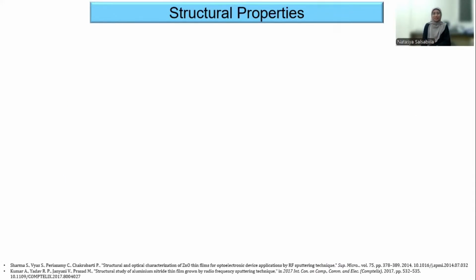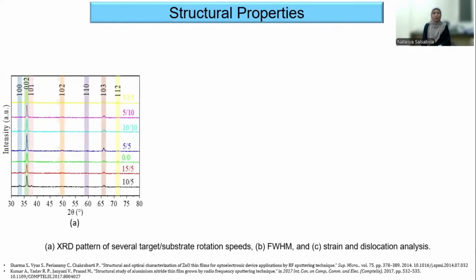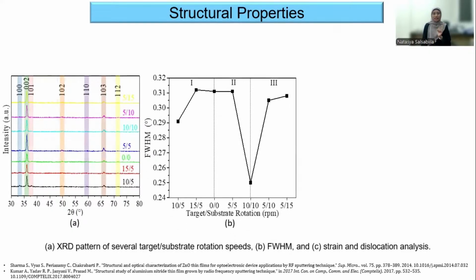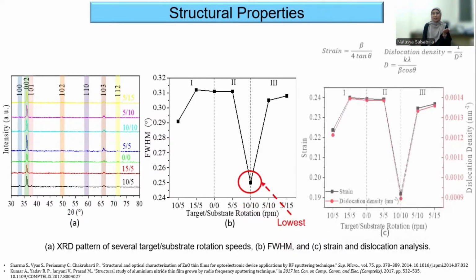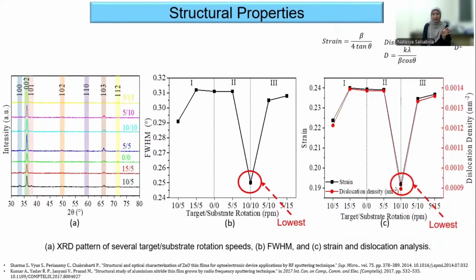Moving to the XRD result, figure A shows the strongest 002 peak at 5 per 5 RPM, indicating a strong Z-axis orientation. However, the 10 per 10 RPM setting, while not having the strongest peak, shows the lowest FWHM, strain, and dislocation density. Lower FWHM, strain, and dislocation density indicate a better crystal quality and lower lattice distortion. Therefore, we conclude that 10 per 10 RPM offers the best overall crystalline quality.